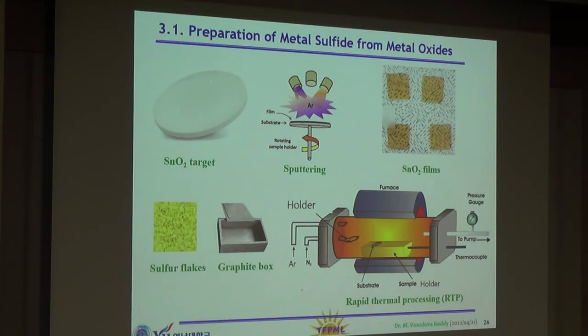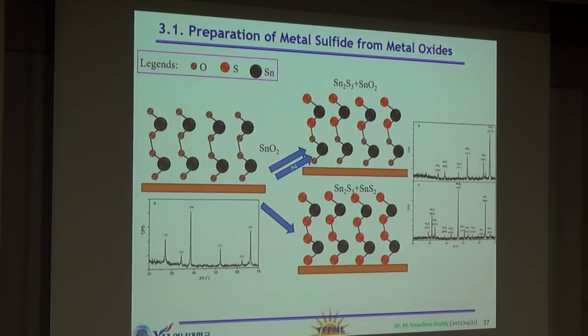First, we prepared the tin oxide layers by using a sputtering process. Here we prepared 500 nanometer tin oxide by sputtering, and then the sputtered tin oxide layers and the sulfur plates together were kept inside the graphite box, loaded into the quartz tube, and then annealed. So we expected the mechanism of the process to be as shown here.